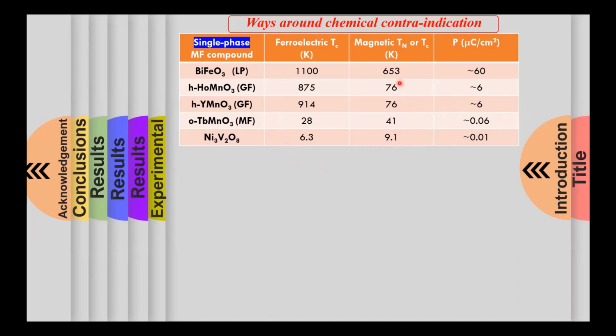Here in this list, for the single-phase multiferroic compounds, we generally see that the majority of the single-phase multiferroic materials have magnetic transition temperature which is well below room temperature. Therefore, these single-phase materials are multiferroic only below room temperature. So from a practical application viewpoint, they are not useful. And moreover, because of this factor, the room temperature magnetoelectric coupling is also very small.